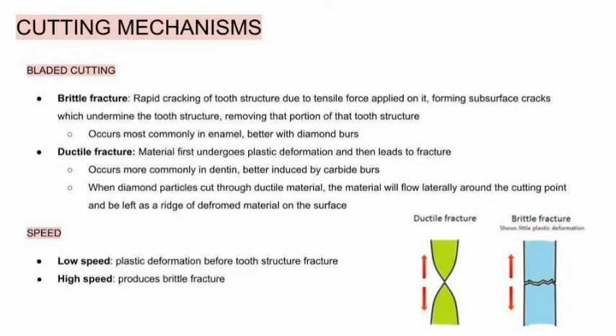The next cutting mechanism that comes into play is bladed cutting. Bladed cutting causes either brittle fracture or ductile fracture. Brittle fracture is the rapid cracking of tooth structure due to tensile force applied on it, forming subsurface cracks which undermine the tooth structure, thus removing that portion of the tooth structure. This occurs most commonly in enamel and is better caused with diamond burrs.